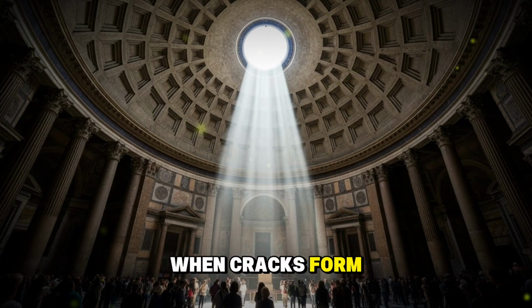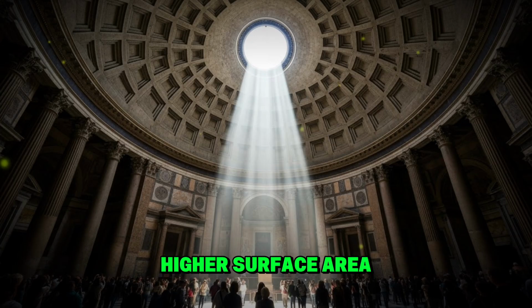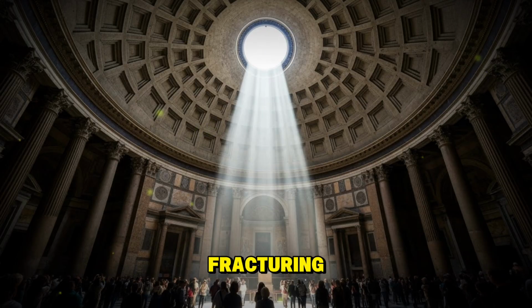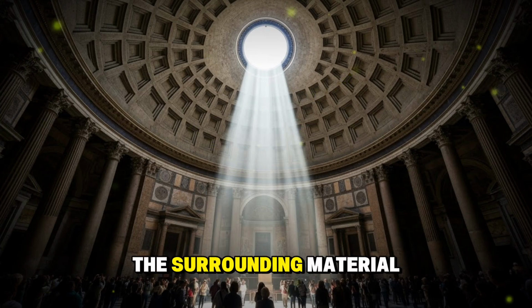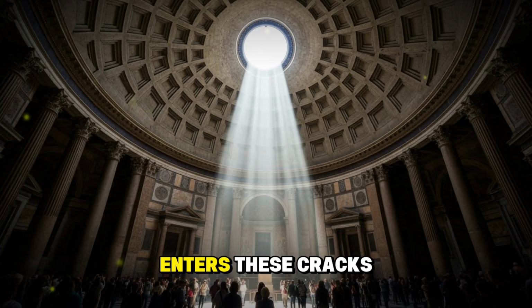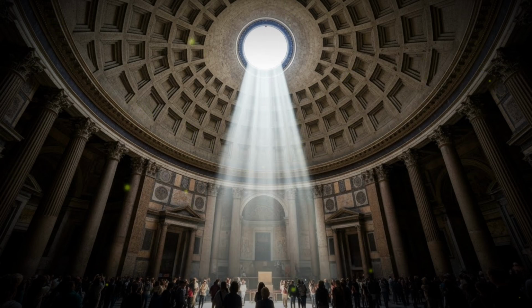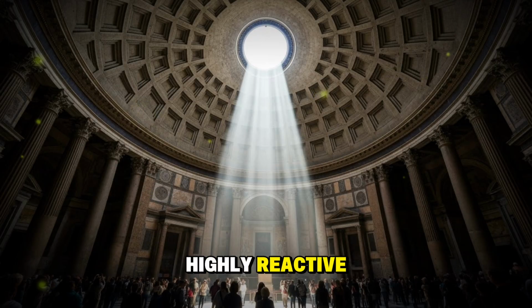When cracks form, they preferentially travel through the lime clasts. This occurs because the lime clasts have a higher surface area than other particles in the concrete matrix. They're more brittle, more prone to fracturing. So when stress creates a crack, that crack tends to propagate through the lime clasts rather than through the surrounding material. Now, when water enters these cracks, it encounters the lime clasts. And here's where the chemistry becomes beautiful. The lime in these clasts is highly reactive.